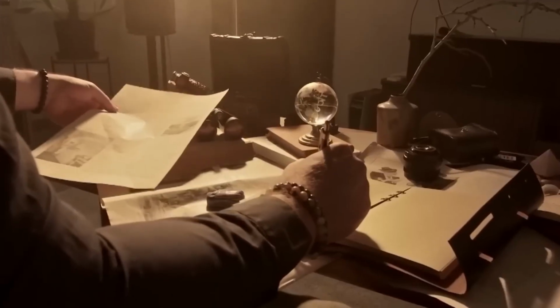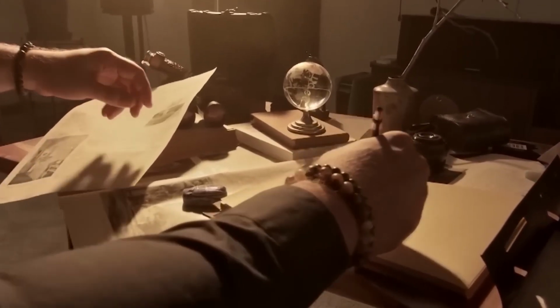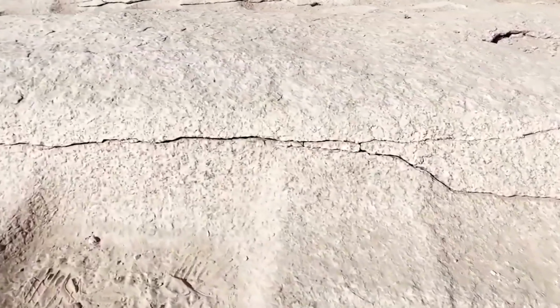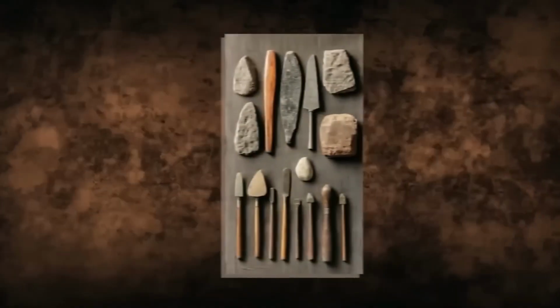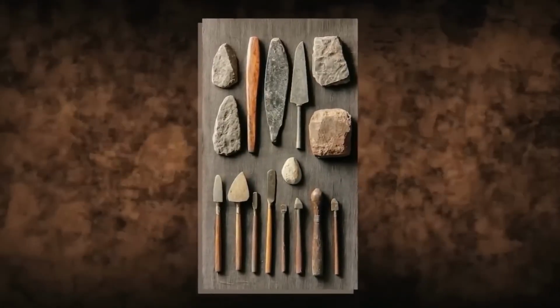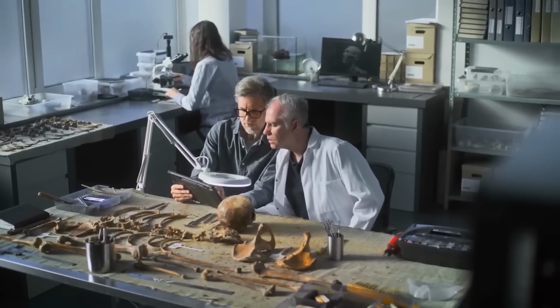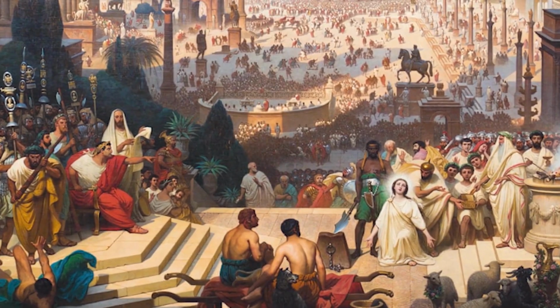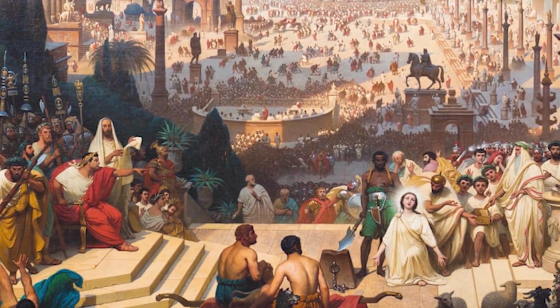Abrasive 3, a corundum quartz slurry. The hypothesis that the microscope evidence had suggested. The results were not close. Copper loaded with sand delivered approximately 0.5 millimeter of cutting depth per hour. Painfully slow, and the copper tools themselves degraded rapidly. The cut surfaces were rough, uneven, and bore no resemblance to the precision found at ancient sites. After a century of repetition as the official explanation, sand produced results that nobody in that workshop would have accepted as adequate. Copper loaded with quartz powder reached approximately 0.8 millimeters per hour, marginally better, still completely inadequate to explain the surfaces and feed rates documented by engineers examining ancient Egyptian granite.